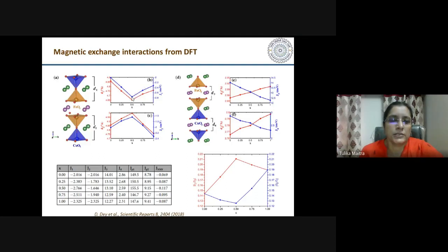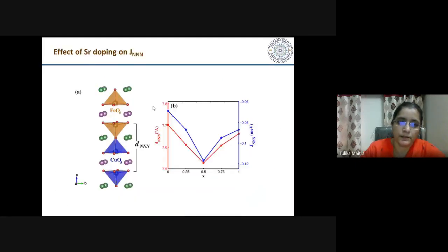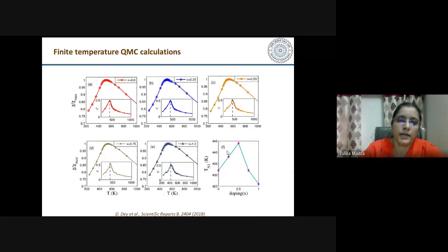The exchange interaction changes with doping and also reverses its trend when it is beyond 0.5. Using these exchange interactions at various dopings, we did a finite temperature calculation using quantum Monte Carlo. We considered a Heisenberg spin model on a cubic lattice and calculated magnetic susceptibility and specific heat to look at how the transition temperature